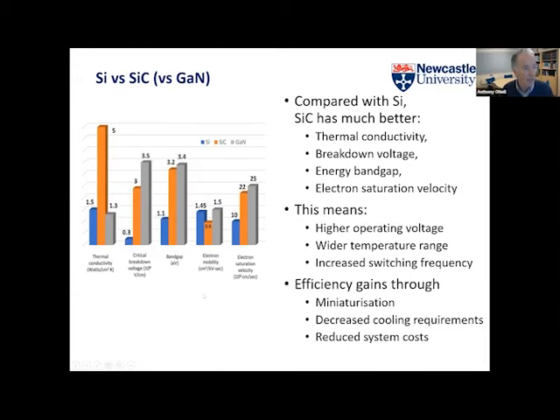And then these are the transport properties. Electron mobility is not quite so good, but velocity saturation is higher, so it depends what you want to pick there. The consequence of that is that you get higher voltage operation for silicon carbide, and I think, as Michael said, you tend to see power electronics splitting between gallium nitride at the lower voltages and silicon carbide at the higher voltages. And you can get a wider temperature range because it's not only a high electric field as a result of the wide band gap, but it means that you can operate to higher temperatures because you haven't got the problem of intrinsic carrier concentration getting too high, for example. So you get a whole load of efficiency gains that way.